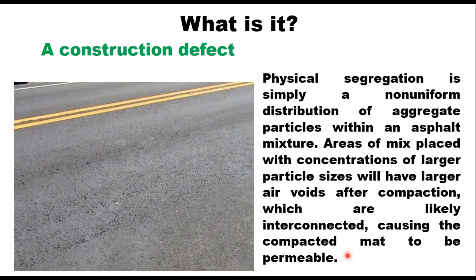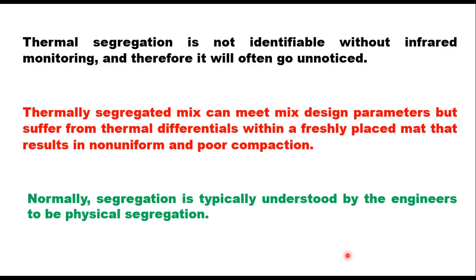Thermal segregation is not identifiable without infrared monitoring and therefore it will often go unnoticed. Thermally segregated mix can meet mix design parameters but suffer from thermal differentials within a freshly placed mat that results in non-uniform and poor compaction.